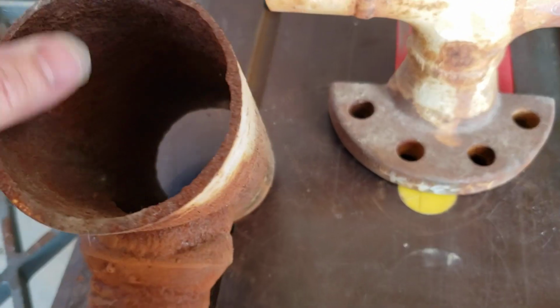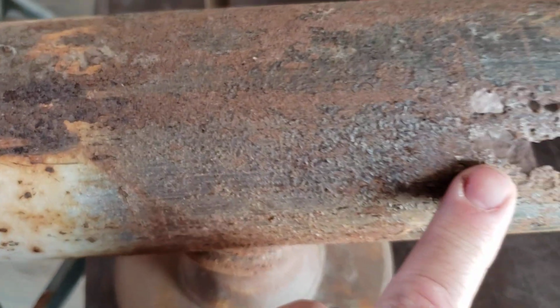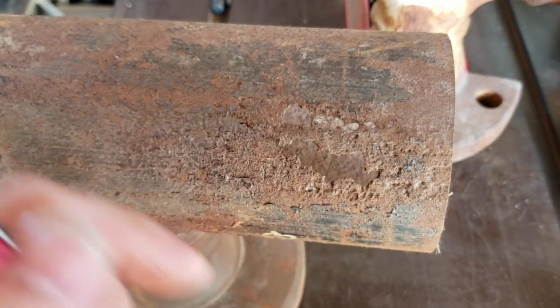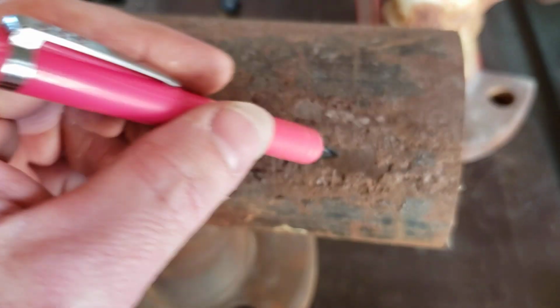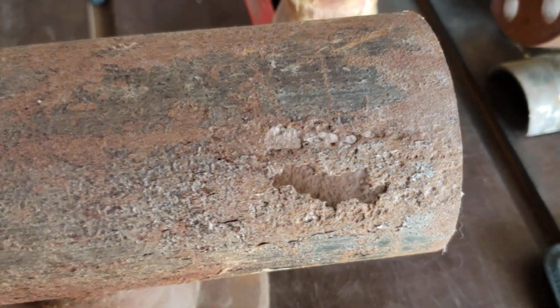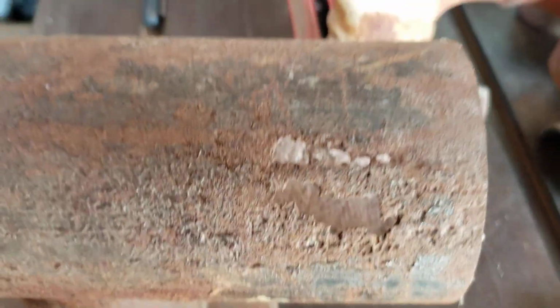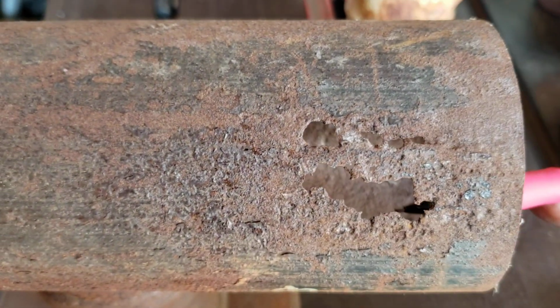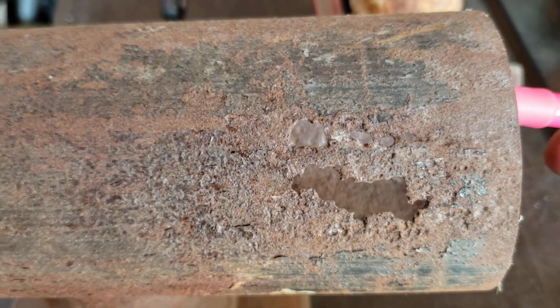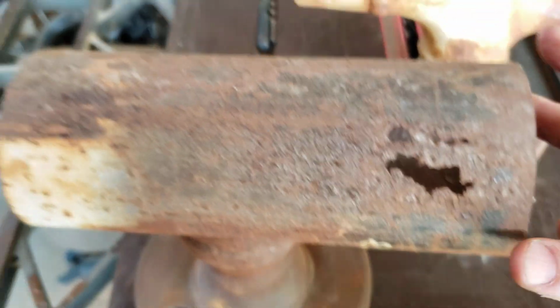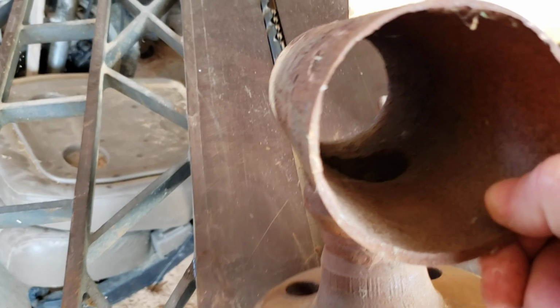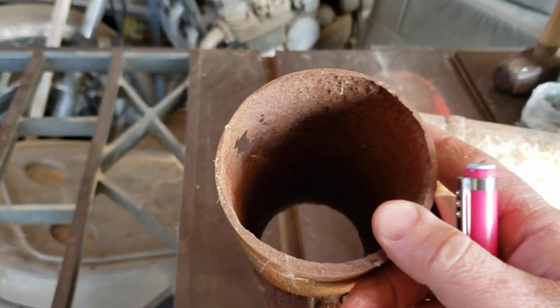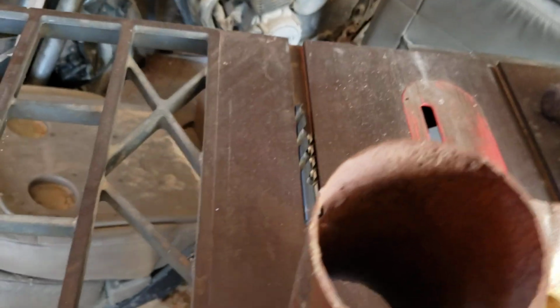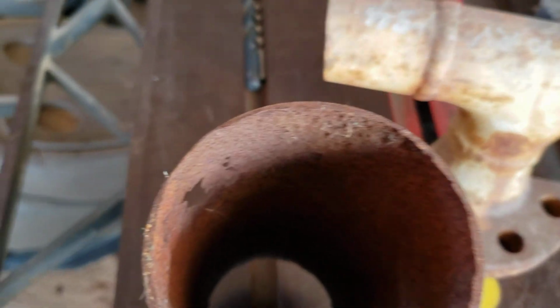How significant? Significant enough that it has a hole in it. And when I mean a hole, I mean through wall corrosion, or complete wall loss, as some people like to say. This was a piece of pipe that was in standard petrochem service, and it was identified as being suspect, and when it was inspected, it was in fact thin. So much so that at this injection point,